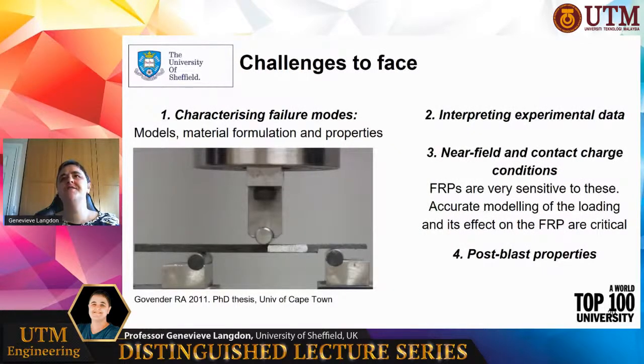Some challenges that we face in fiber-reinforced polymer research are trying to characterize the failure modes and understand how to formulate the material so that we can model them. This is particularly difficult for fracture. So what you see on the screen there is an attempt at a single leg bend test, which we try to do at high speed to try and characterize the opening of the fracture in a composite material which has two parts with a crack already initiated in it.